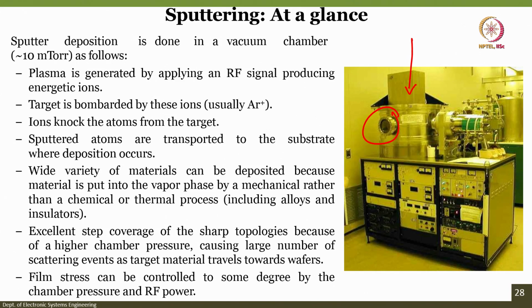This is done generally in a vacuum chamber, at about 10 millitorr. The plasma is generated by applying an RF signal producing energetic ions, if it is RF sputtering, and usually the target is bombarded by these ions, that is, argon ions. Argon is a gas that is used in sputtering. The ion knocks the atom from the target and the sputtered atoms are transported to the substrate. We are talking about these things many times, right, so that we do not forget that this is the mechanism by which sputtering works, right. A wide variety of materials can be deposited because the material is put into the vapor phase by a mechanical rather than thermal process, this is extremely important, right.